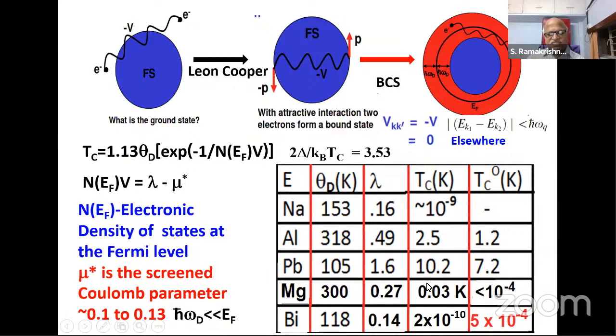Magnesium, of course, is a question where people predict 30 milli K. We have gone down to 100 microkelvin. We don't see anything. Bismuth is the other way around. The theory predicts it should be at 0.2 nanokelvin, whereas the experiment I will show you, it's at 500 micro K, 0.5 millikelvin. So it's off here. That is because the theory is not applicable here. So you can't use the same theory for a case where things are not applicable.